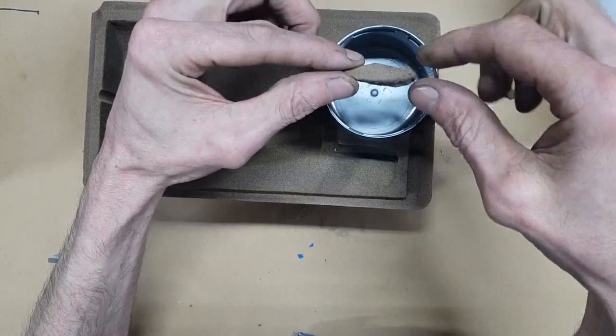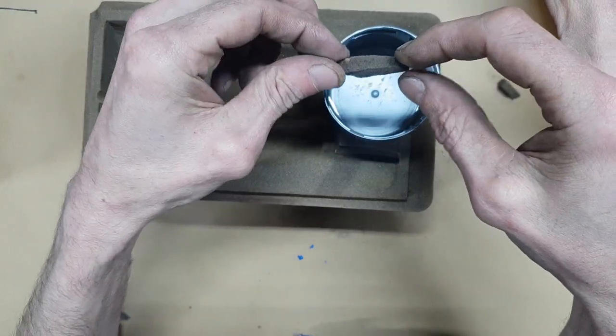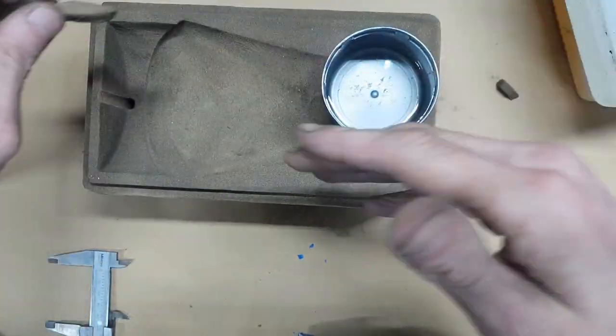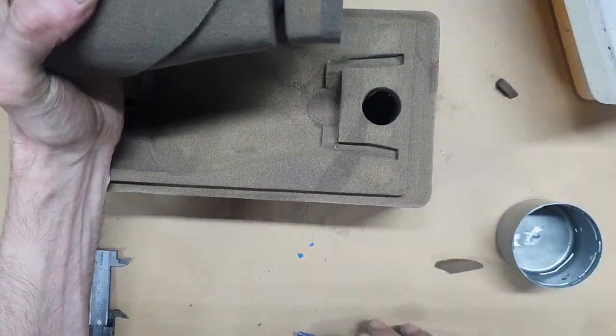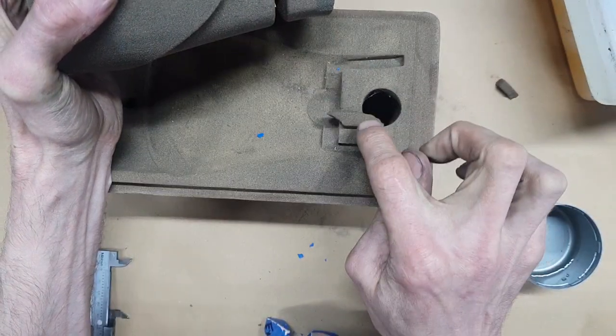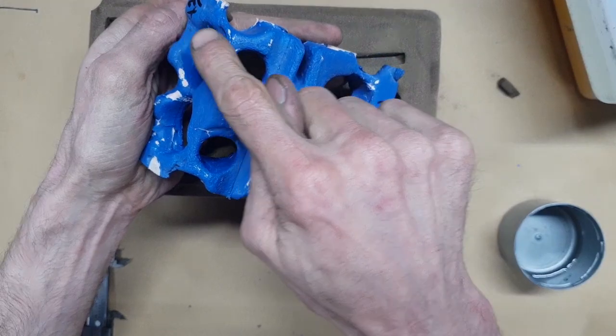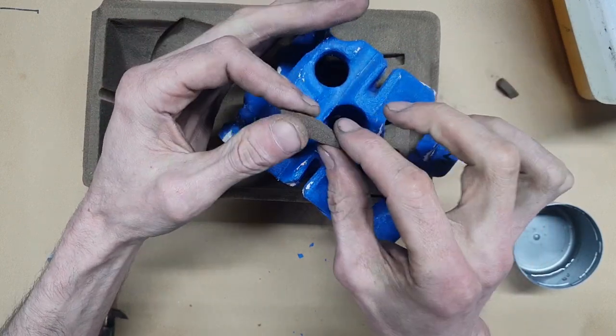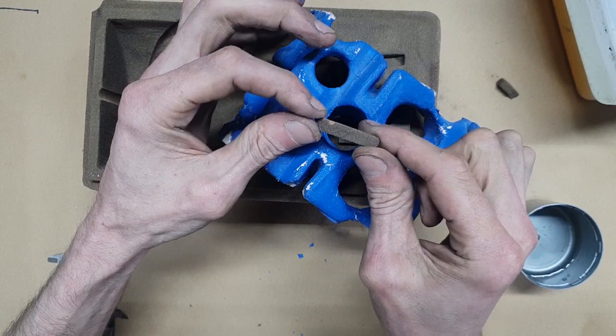The thing with the binder and this sand is, when the mold is finished or when the part is poured, you put it into water, not to cool it, but to dissolve the sand. So water will break down the binding agent between the particles, which will then let you flush out the sand. From the outside, you can smash off a lot of this or it'll come off, but an inner core, if that was an inner core of sand, you need to wash all this out of the cylinder head. So it's important that this is easy to dissolve, which was a big thing in 3D printing, because it needed to be flushed out easily. You could have a huge area left that didn't flush out, and number one, that wouldn't get cooled if it wasn't flushed out, and number two, if it did start moving when you were machining it or when the engine was running, all this would end up in your water pump. So you don't want sand in your water pump.